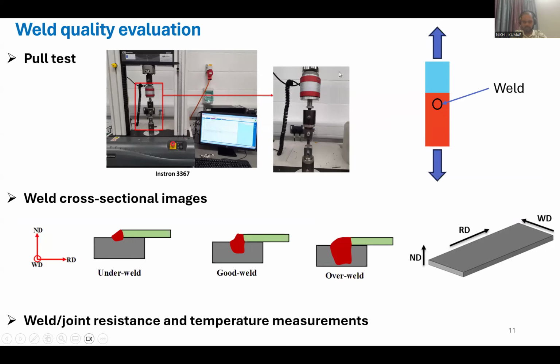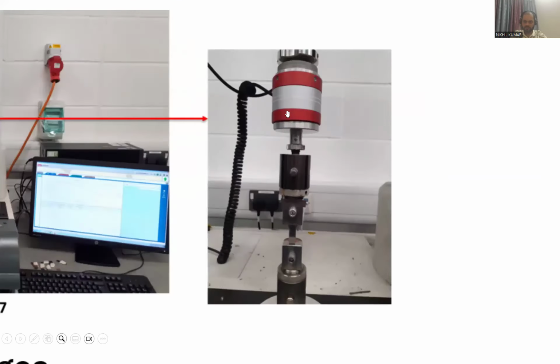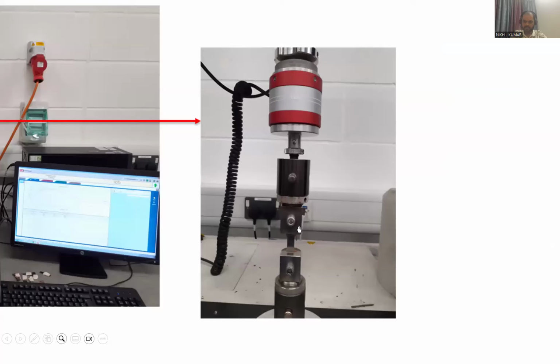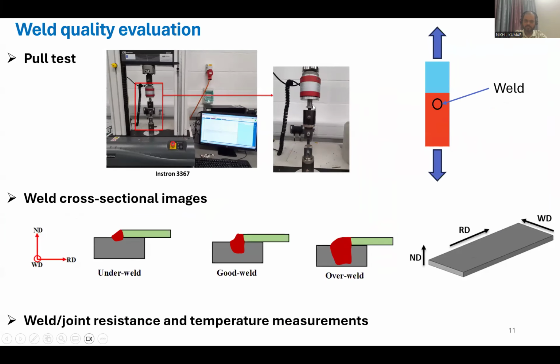And how is the weld strength captured? This is captured in the load cell. You can use a load cell and capture the resistance. This is the specimen, and it is gripped on the bottom. The bottom is stationary, and this one is moving on the top, and it is capturing the strength, or you can say the maximum load is captured using the load cell. This way, you can capture the strength and say whether it's a good or bad weld, depending on whether it's failing from the tab or it's an interfacial failure.